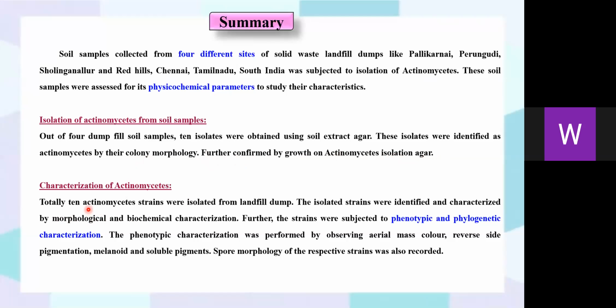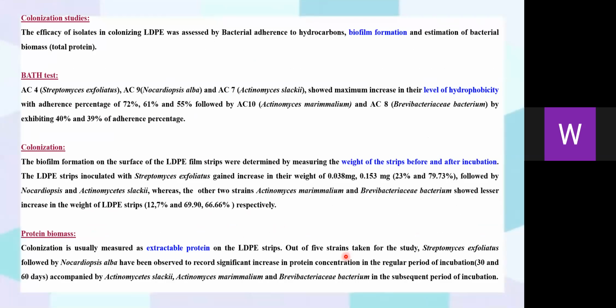Characteristics of actinomycetes. Totally 10 actinomycete strains were isolated, identified and characterized by morphological, biochemical, phenotypic and phylogenetic characterization. Phenotypic characterization was performed by observing aerial mass color, reverse side pigmentation, melanoid pigment, and soluble pigments. Spore morphology of the respective strains was also recorded. Colonization studies: BATH test, colonization and protein biomass were assessed. BATH test: AC4, AC9, Streptomyces exfoliatus, Nocardiopsis alba, and Actinomyces slackii showed maximum increase in hydrophobicity with percentages of 72, 61, 55, followed by the other two strains, Actinomyces marimmalium and Brevibacteriaceae bacterium.